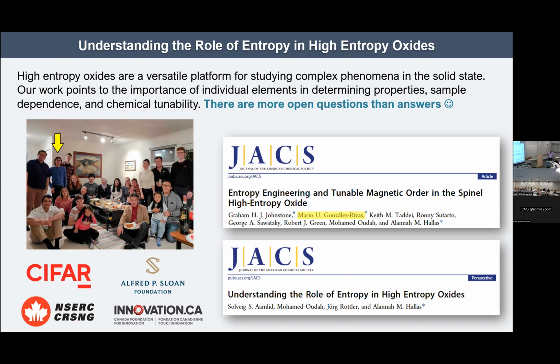That's interesting. So you use a different synthesis technique, but still all of them were done more or less in air. Yes, in air. Because of this valence, it can be sensitive to oxygen partial pressure. If you change the oxygen partial pressure very much, then this valence may change, and then the entropy and all these things could change. That's right. We've done quite careful thermogravimetric analysis, and they actually do differ quite a bit in their oxygen concentrations. But still the preference is overall for entropy. I see. Okay, interesting.